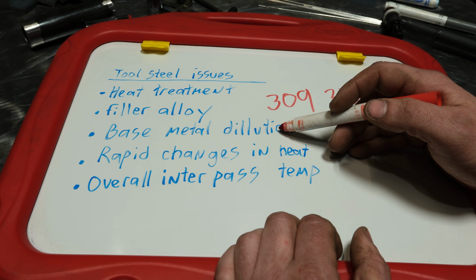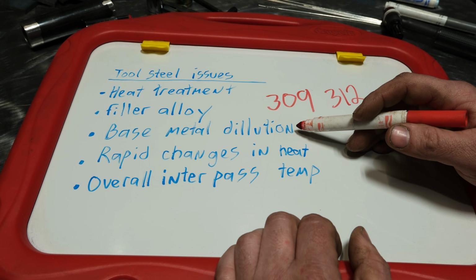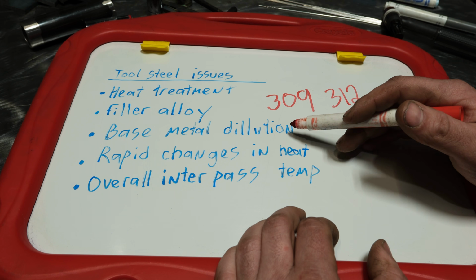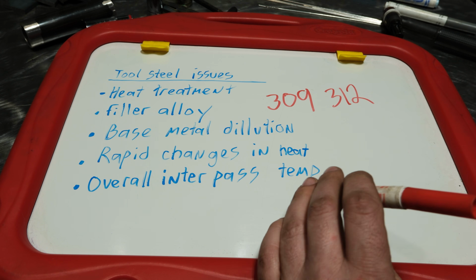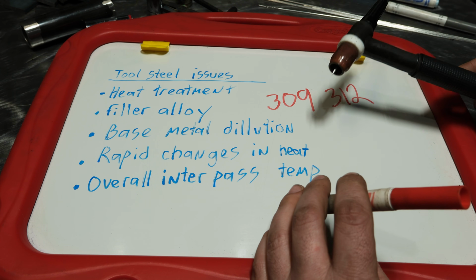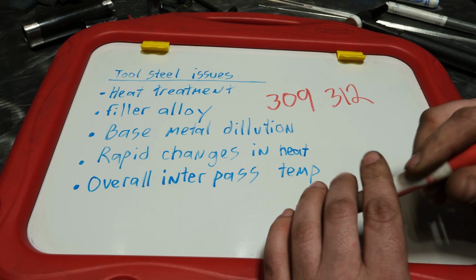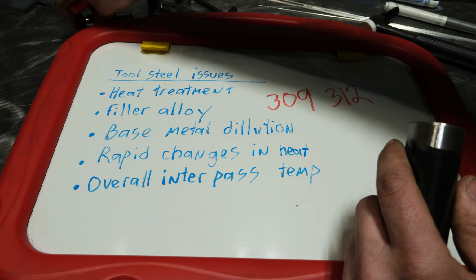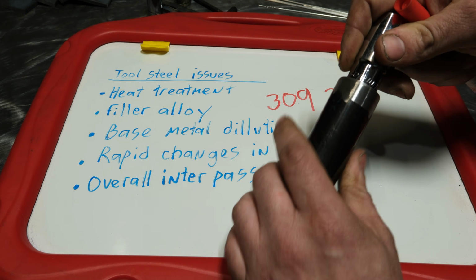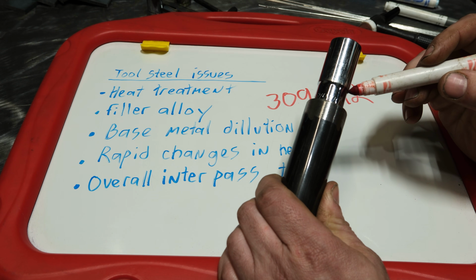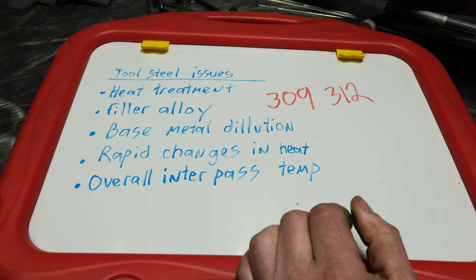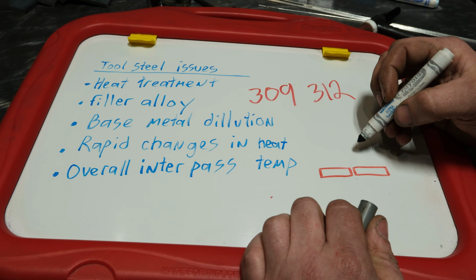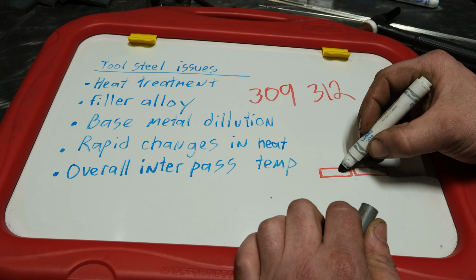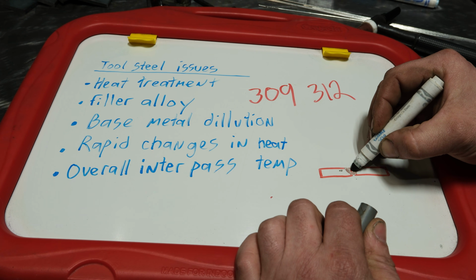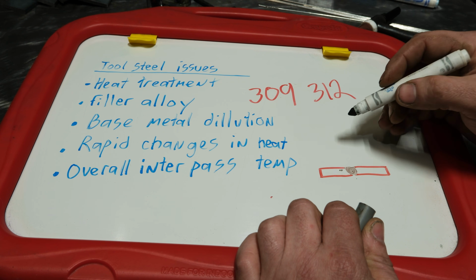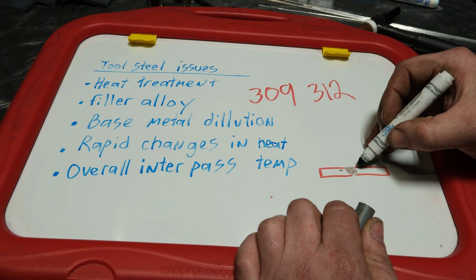Now, another thing you need to be aware of is what I call base metal dilution. And this is something a lot of people completely overlook or don't even know it exists. And this is more of a problem with TIG. With TIG welding, because you have a torch that can basically melt metal separate from your filler, you can take something like, say, this socket, put it in here, and if you don't add enough filler and you're just melting this material together, you can get what I call base metal dilution. And with base metal dilution, you wind up melting your base materials together into a weld nugget, and without enough filler, an alloy, that filler, that 309 or 312, you can produce a very brittle weld.